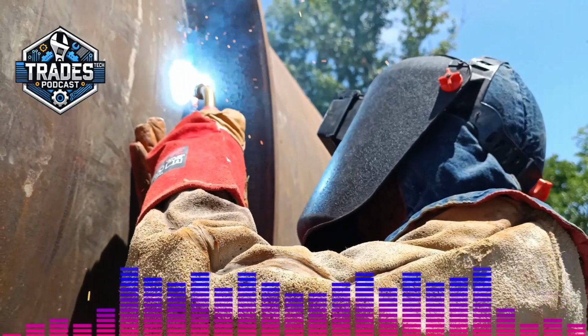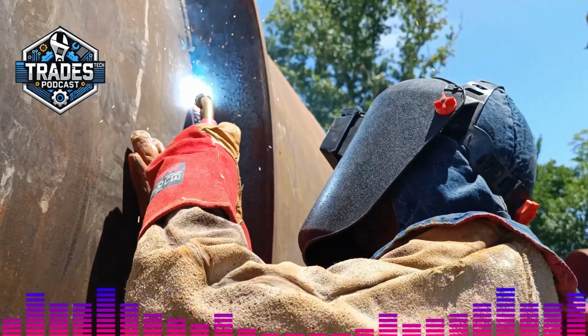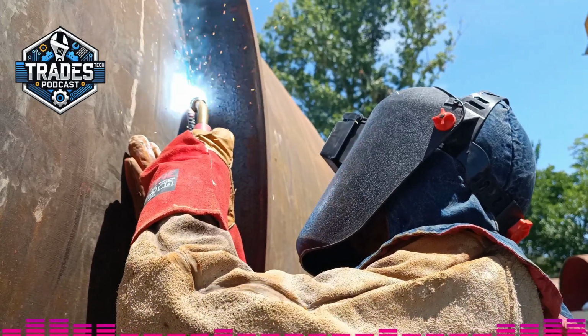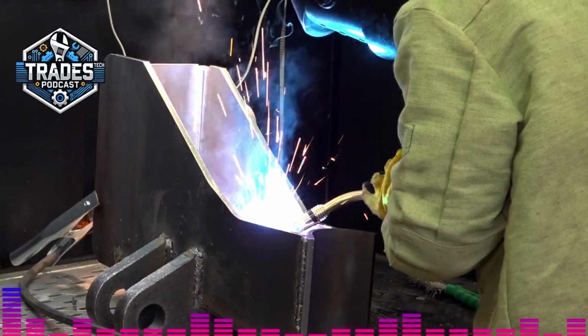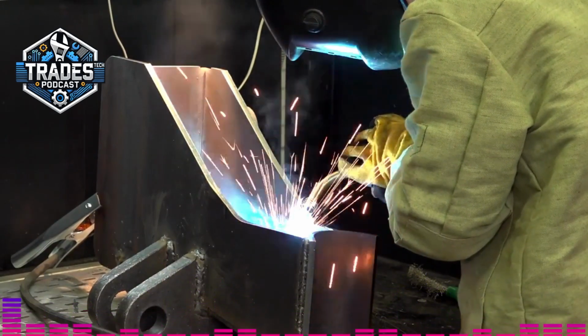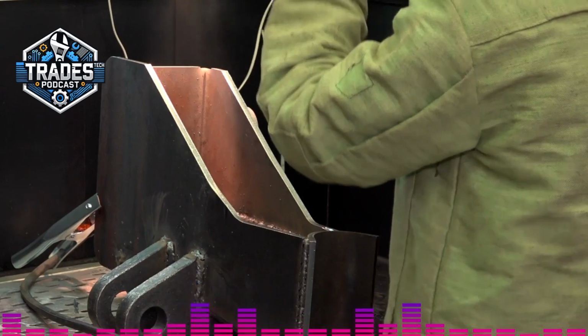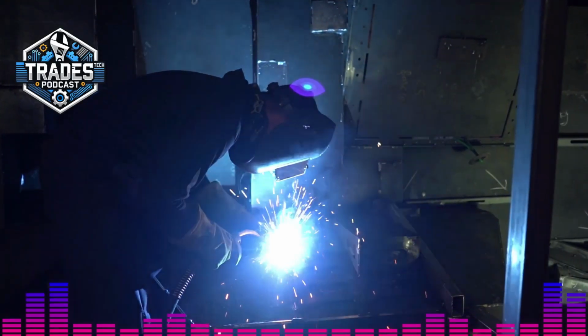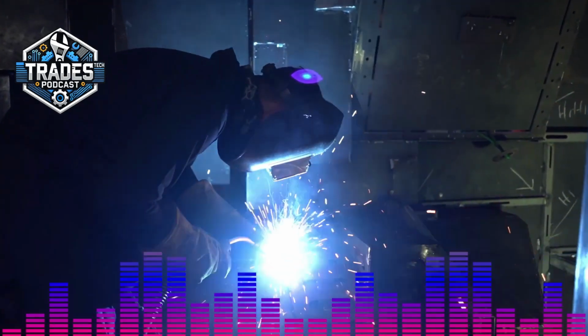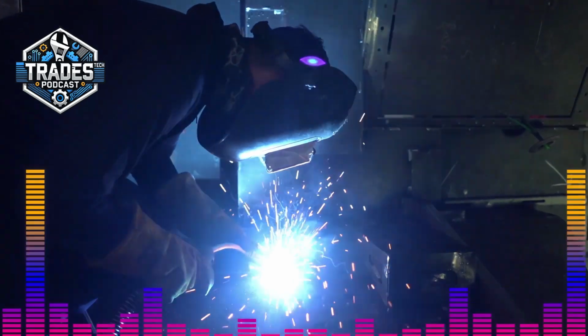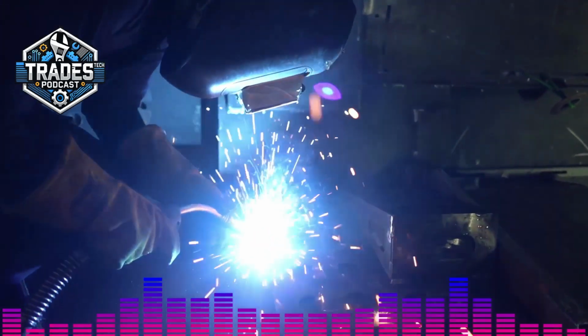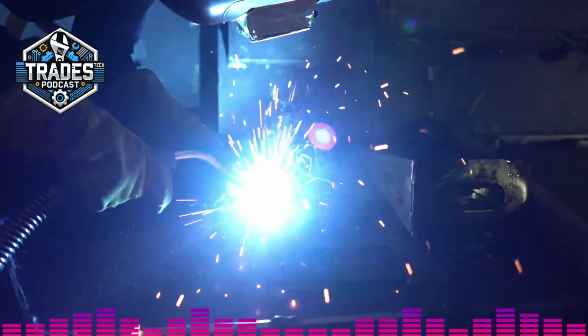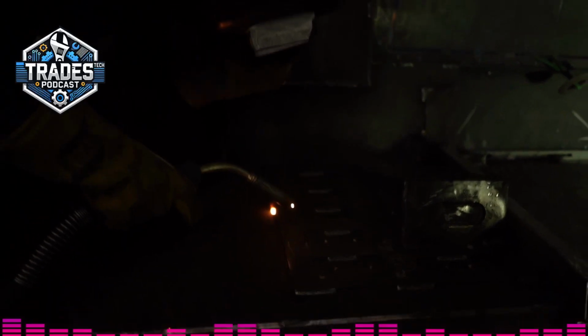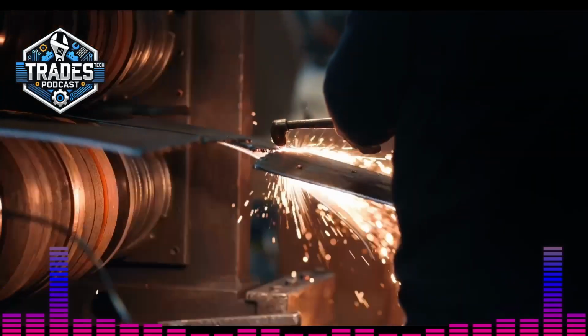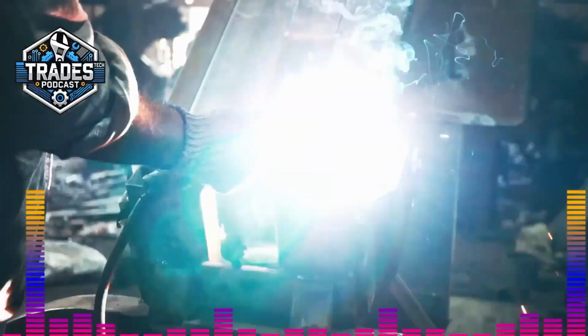Beyond the environmental tolerance, FCAW also brings some significant performance advantages, especially when you compare it to MIG welding on thicker materials. Let's talk about speed, penetration, and portability. These are key factors that contribute to FCAW's popularity in heavy fabrication. For speed, FCAW generally boasts higher deposition rates than MIG welding. This means you can lay down more weld metal in a shorter amount of time. Industry benchmarks and welding procedure specifications often indicate that FCAW can achieve deposition rates that are 20% to 50% higher than traditional MIG welding, particularly in out-of-position welding like vertical up or overhead. This translates directly to increased productivity and reduced labor costs on large-scale projects.